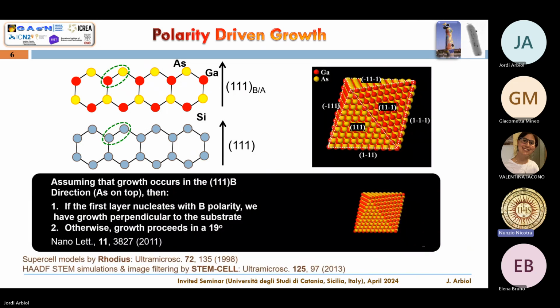But then let's take this typical octahedron. This is showing all the possible 1-1-1 facets that you can get in this cubic structure of gallium arsenide, okay? The red ones are the ones terminated in gallium, the cation polarity. And the yellow ones are the ones that are showing the anion polarity, terminated in arsenic. So if the first nucleation seed that is falling on top of the silicon is terminated in an anion facet, an arsenic facet, then you will be able to grow a vertical nanowire. That is easy because we will have the anion surface just liberated and you can grow on top.